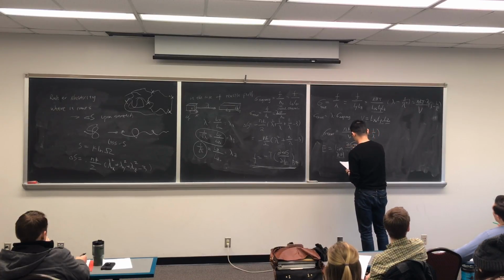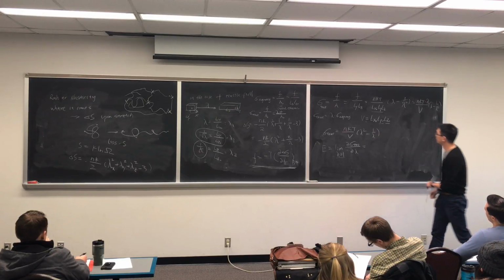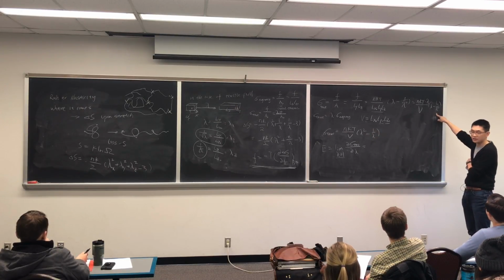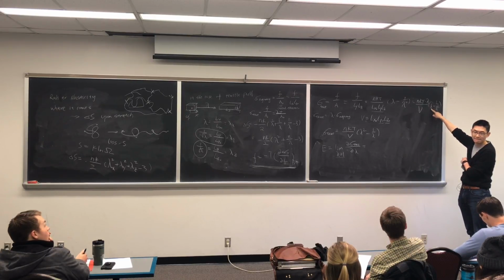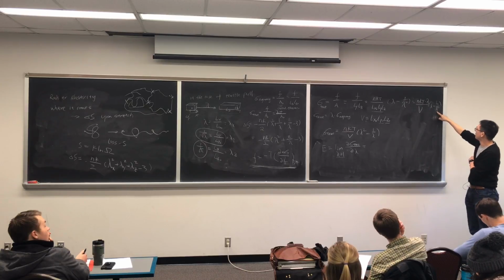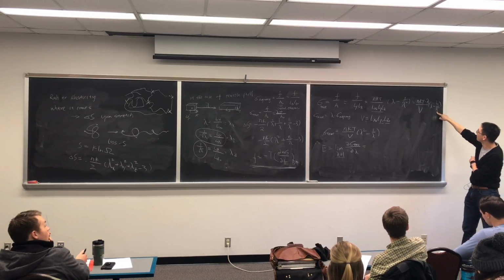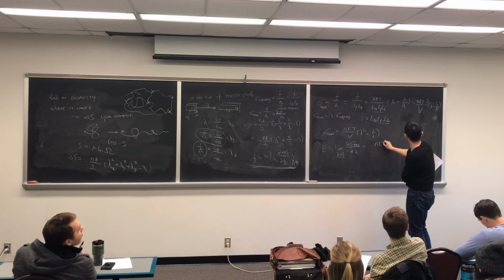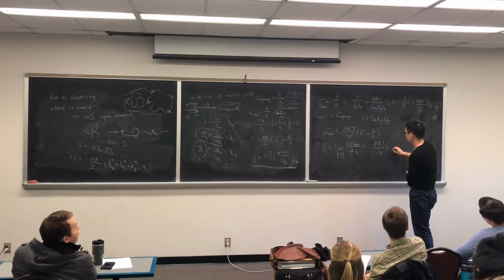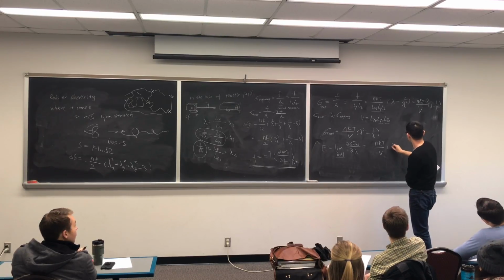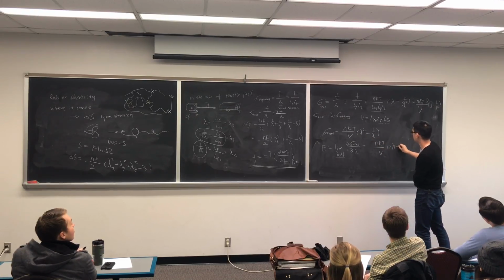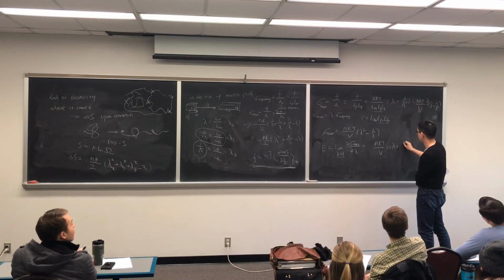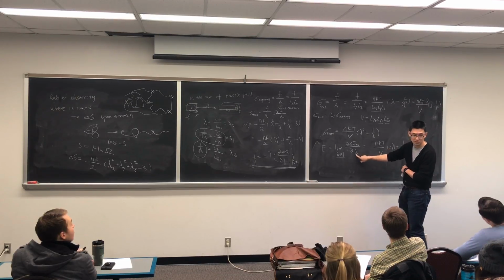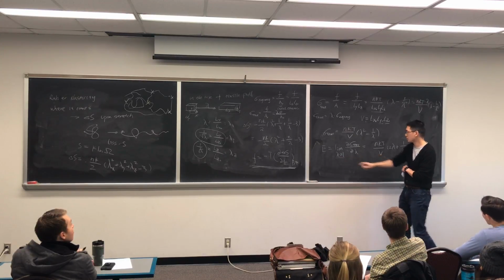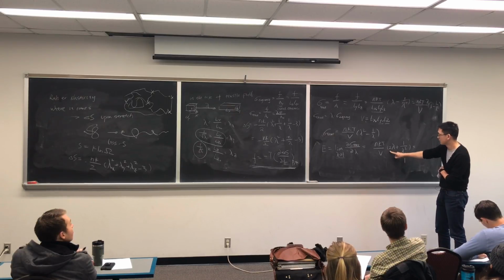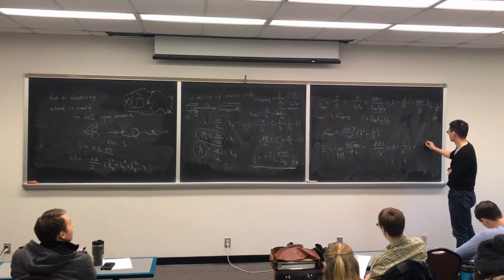Divide by lambda, and we have a relationship right here. If you take the partial derivative with respect to lambda, this will become 1. 1 minus 2 lambda will become, let me do it here. So we will have nkT divided by V, so this will become 2 lambda. This will become minus or plus 1 plus lambda squared, right? If you take the partial derivative. And when lambda approaches 1, this will be 1. 2 multiplied by 1 will be 2.